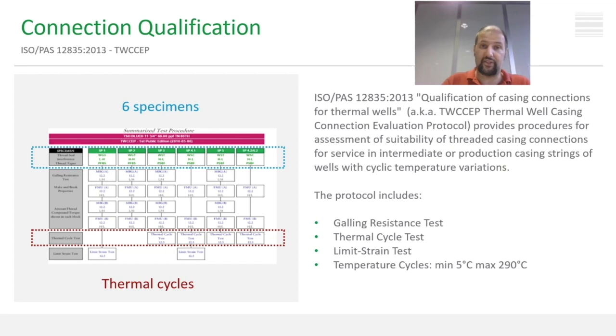Even if it became an ISO standard in 2013, the schematic you see refers to a qualification protocol performed in our labs already in 2010. The test was performed on 6 different samples with extreme tolerance configurations, tested for galling resistance with make and break, and then submitted to pressure temperature cycles. For 2 of the 6 samples, strain-based limit loads are also requested. As we already saw, strain-based criteria and tests are a key factor for geothermal applications.